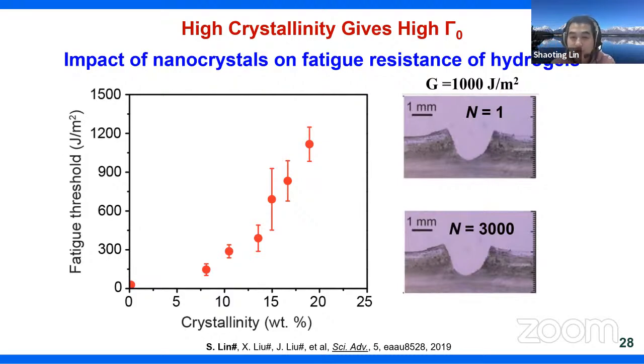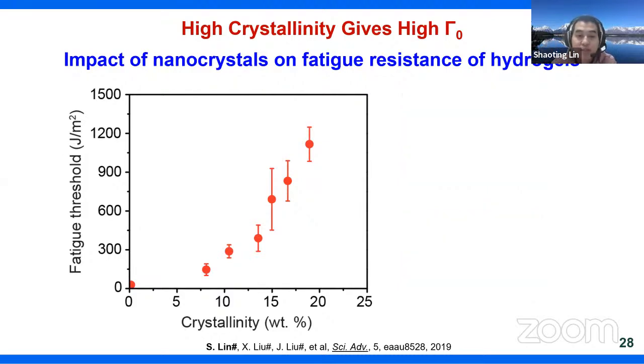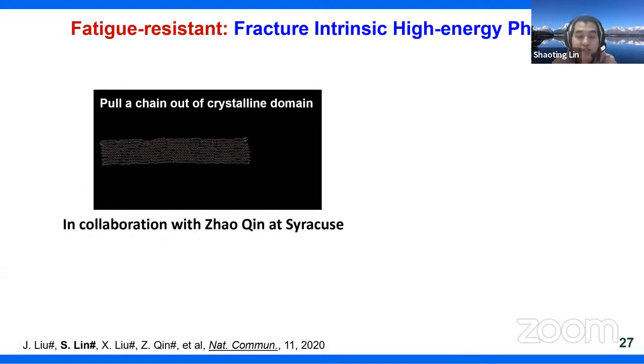The second question is about the crystal domains. The impact of crystal domains on toughness is not new; it has been studied a lot. The basic mechanism absolutely enhances toughness. The basic mechanism is the melting of the crystal domains. By melting of the crystal domains, it provides a large hysteresis loop, and the presence of a large hysteresis loop dramatically enhances toughness. This goes back to the first part of my discussion, on why the presence of a hysteresis loop promotes high toughness. So this is how the crystal domain enhances toughness.